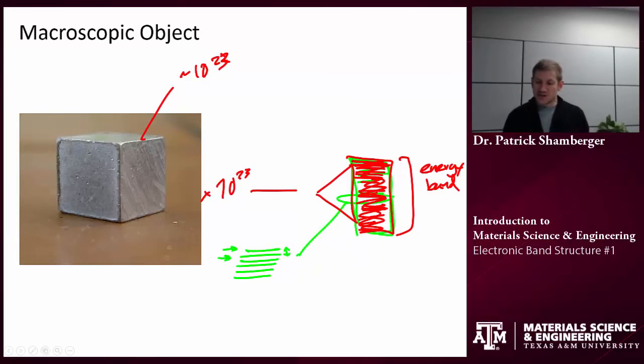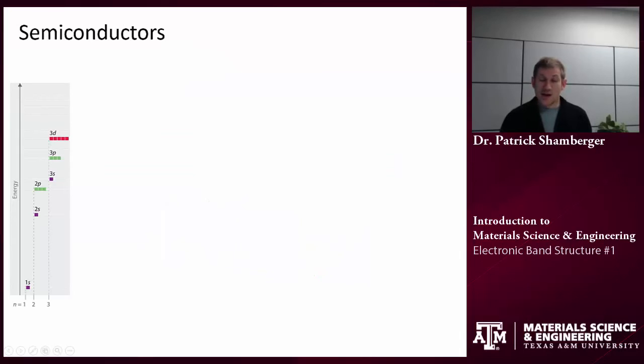So when I'm talking about an energy band, I'm talking about a large number of very closely spaced energy levels. That was a sodium atom. In that case, we're thinking about mixing together only these 3s orbitals. And they lead to one continuous band. It gets a little bit more complicated as we think about some of the traditional semiconductors. So something like silicon is going to have 3s and 3p electrons. And so these are both going to be valence orbitals.